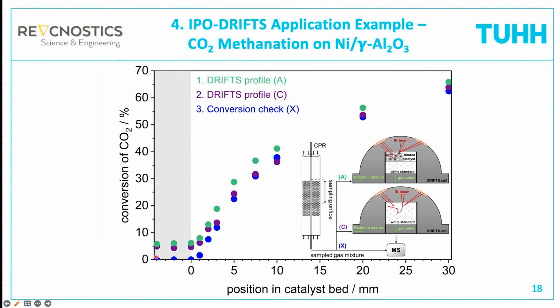So in this plot, you can see now the conversion profiles measured once behind the CPR, so at the outlet of the sampling capillary. These are the blue dots. And you see that before we drive into the catalyst bed, there is no CO2 conversion. And then as we drive down the catalyst bed, we get an increasing CO2 conversion, as you can see here.